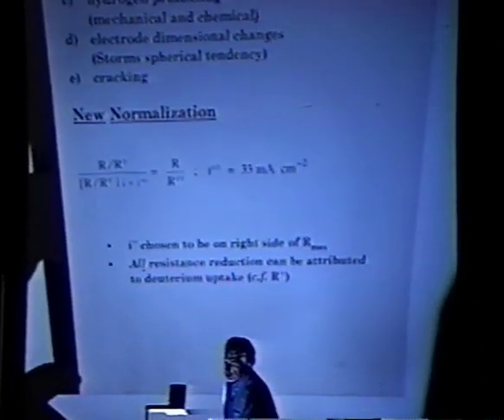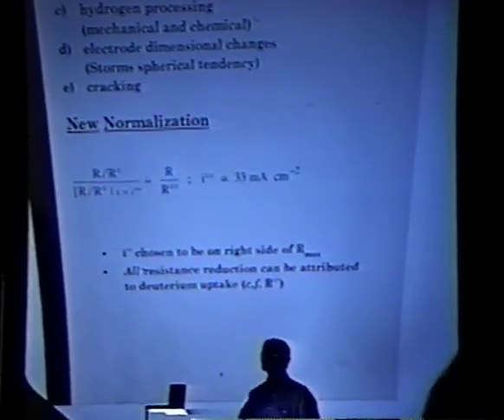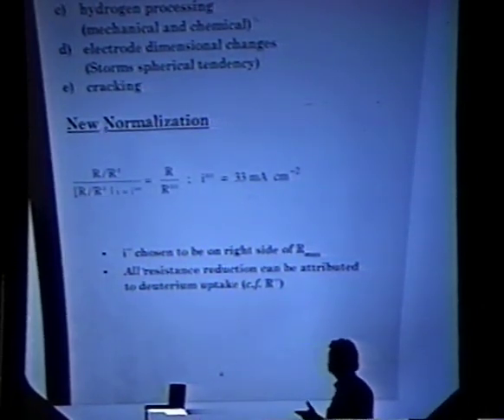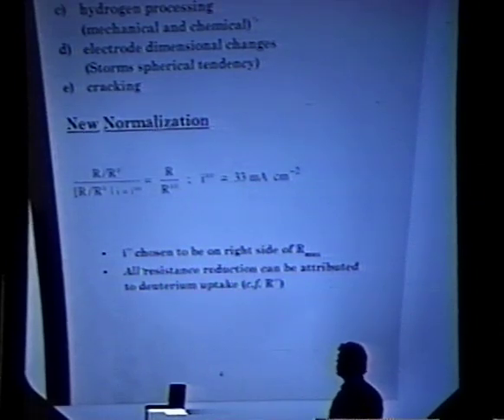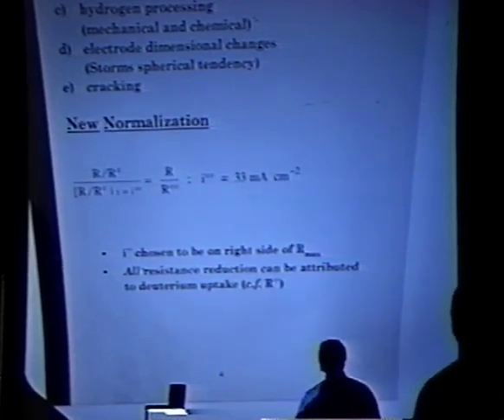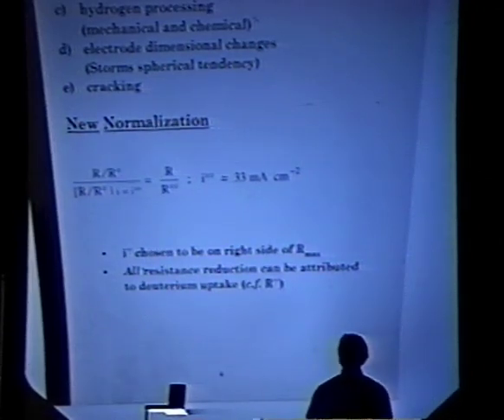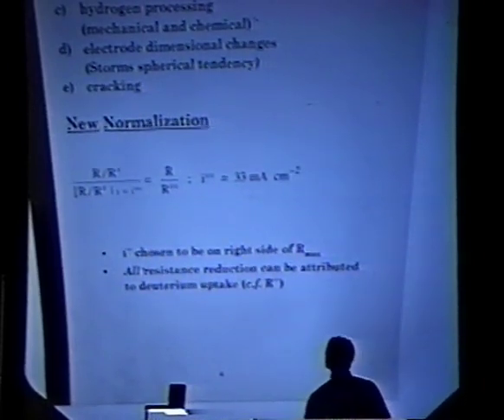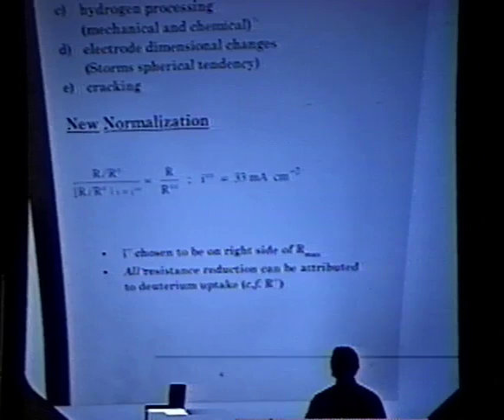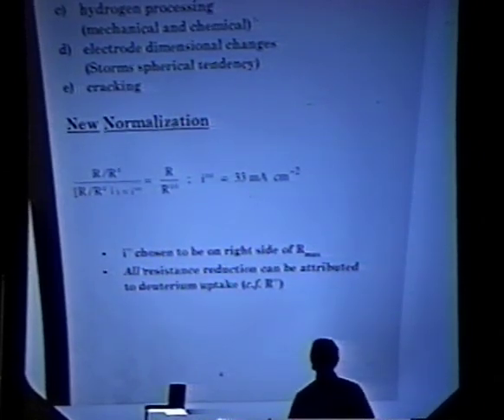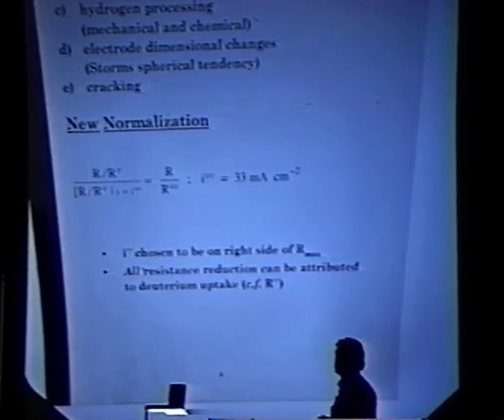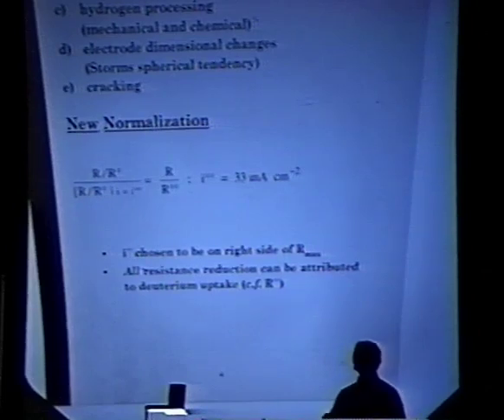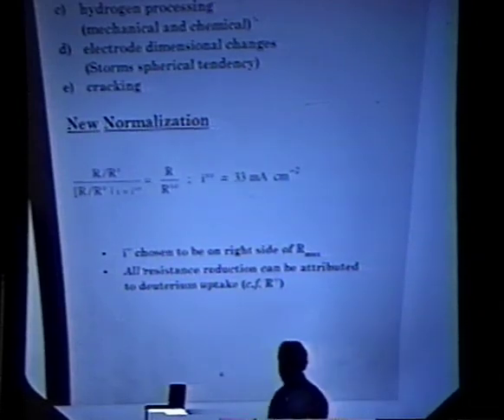In an attempt to avoid all of the variables which affect the resistance, other than the one that I'm interested in, I've attempted a new normalization of the data. I've simply taken the resistance ratio as measured, divided by the resistance ratio of the electrode under some standard condition, and I've arbitrarily selected as a standard condition 33 milliamps per square centimeter. So what I'm saying is that the electrode has achieved its equilibrium state of loading at 33 milliamps per square centimeter. I chose that to be on the right-hand side of the resistance maximum, so that all reductions that we observe in the resistance ratio can then be ascribed to the uptake of deuterium, and deuterium alone,